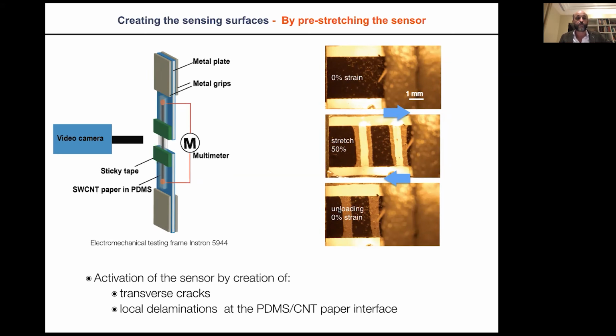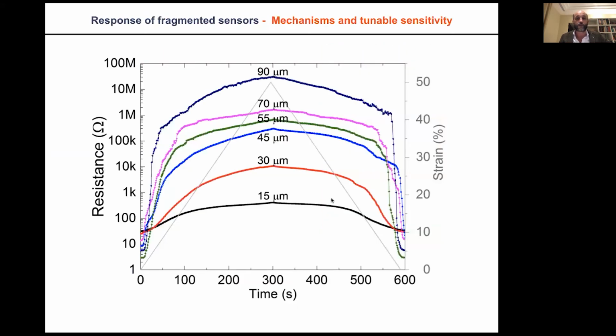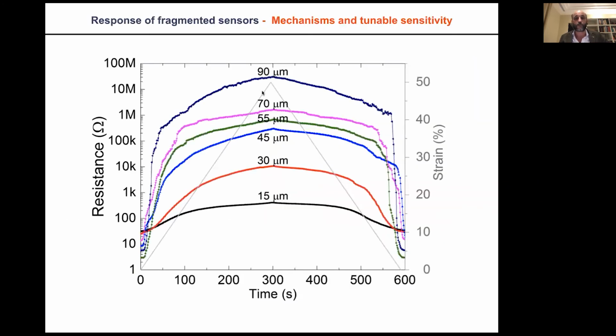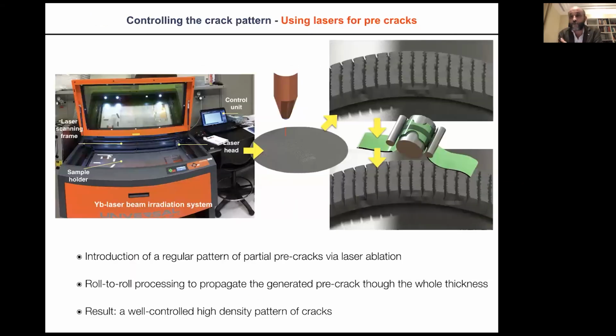The thing that is impressive in this kind of sensors, when you look at the technology, is that the gauge factor can be very big. Here, for example, if they experience a strain cycle up to 50%, you see that the resistance of these sensors is going to change from a couple of ohms to a couple of mega ohms, but without any loss of conductivity. That means you can, from the beginning to the end, control your sample, and this is typically the kind of response that you are going to get. Of course, when you look at this curve, it's not very linear. There is a strong variation of sensitivity in this regime, and one way to control the linearity is to control the morphology of the cracks.